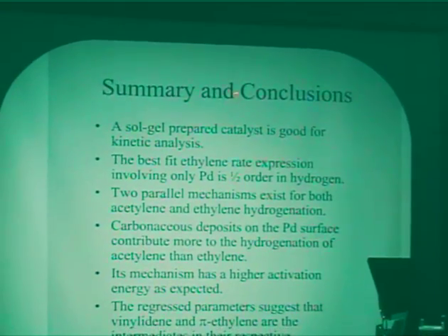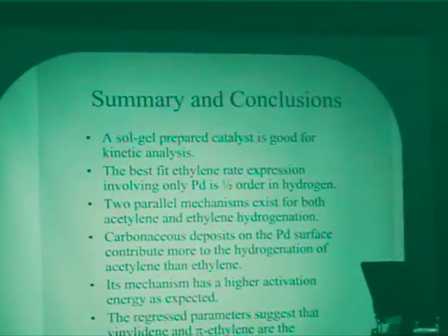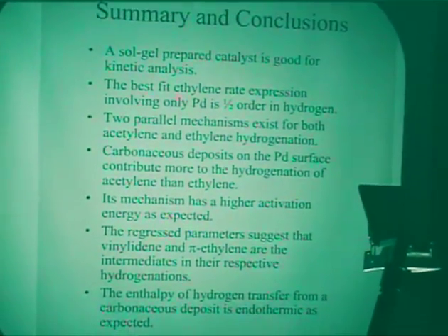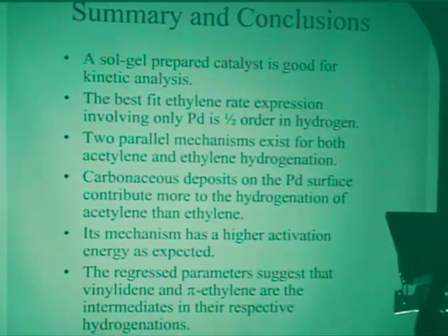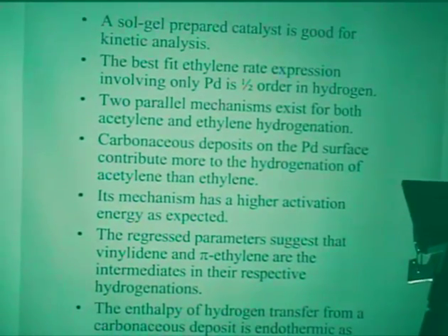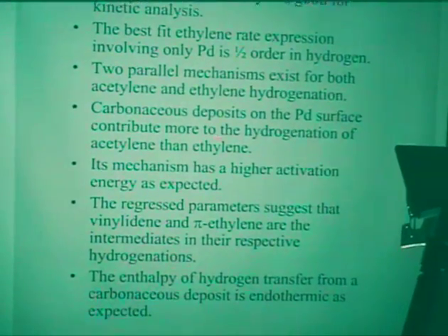So quickly, the summary and conclusions. We used a sol-gel prepared catalyst. This is good for kinetic analysis. The best fit ethylene rate expression involving only palladium is approximately half order in hydrogen. We found that two parallel mechanisms exist for both acetylene and ethylene hydrogenation, although it seems to only be important for acetylene.